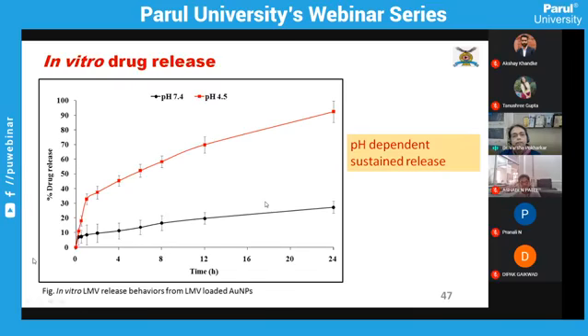The in vitro drug release was carried out using the dialysis bag method, and we could see here that at pH 7.4, the plasma pH, there was very little release. However, at the acidic pH of 4.5, which could be the pH present in the endosome, once the particle is taken up by endosomal or lysosomal uptake, it will go inside the endosome where there is an acidic pH range of 4.5 to 5, and the drug release is going to take place.